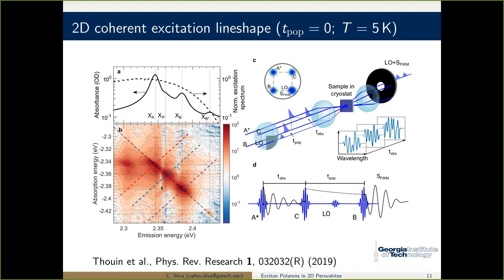But you see several things. You see cross peaks between the different excitons. That means that they are correlated. They share a common ground state and also a common excited state. They're an intrinsic part of the electronic structure of the system, but we've already decided that they're distinct. And in this experiment, in this particular geometry, I can also separate homogeneous and inhomogeneous contributions to the total line width. I'm interested in measuring the homogeneous contribution because that tells me what the dephasing rate is. In the density regime that we are in, if I have an exciton here and another exciton here, they feel the Coulomb correlations amongst themselves and with the rest of the lattice, as I've just mentioned. This is going to lead to resonant elastic Coulomb scattering, which leads to dephasing. So I want to measure the dephasing for each of the excitons individually, and I can do that with this experiment.